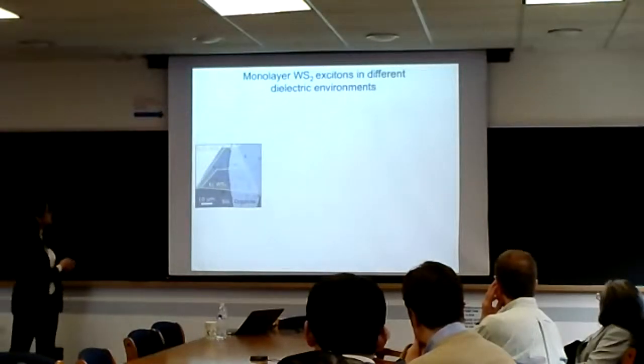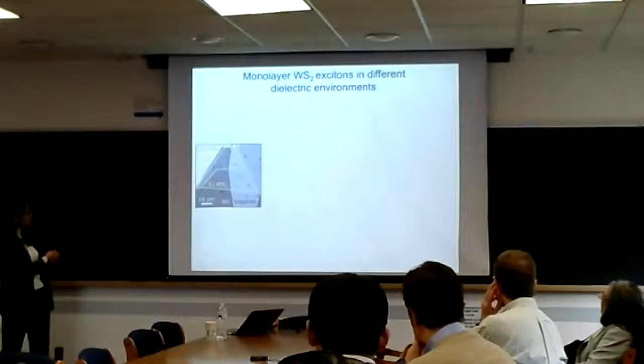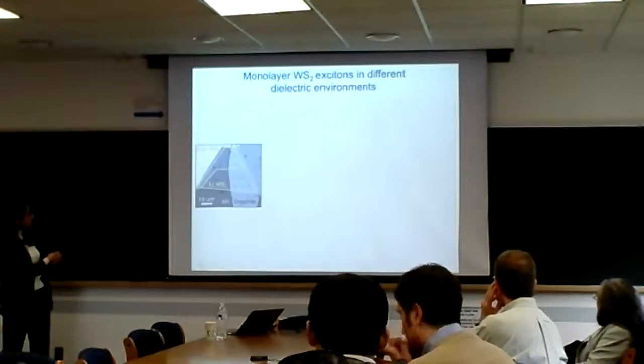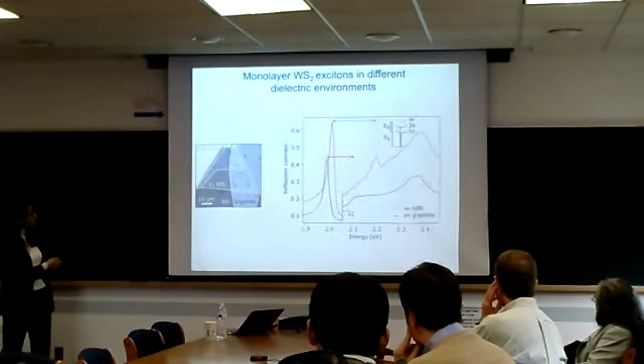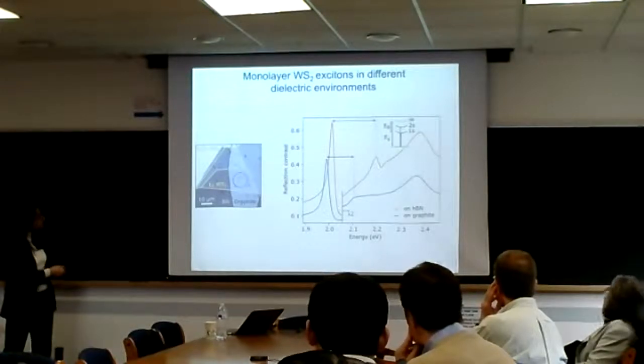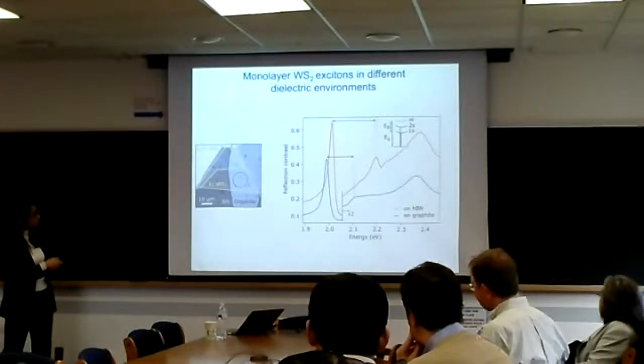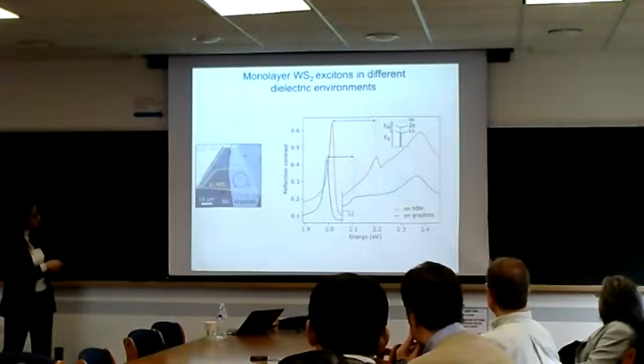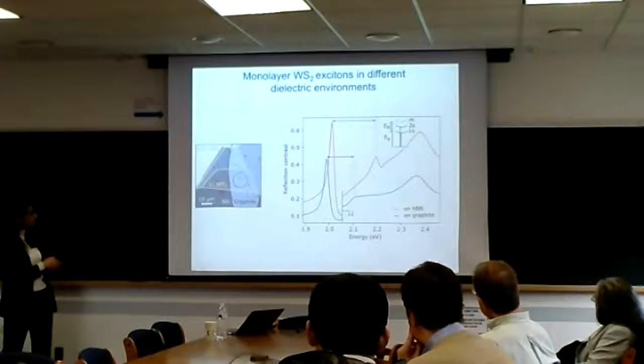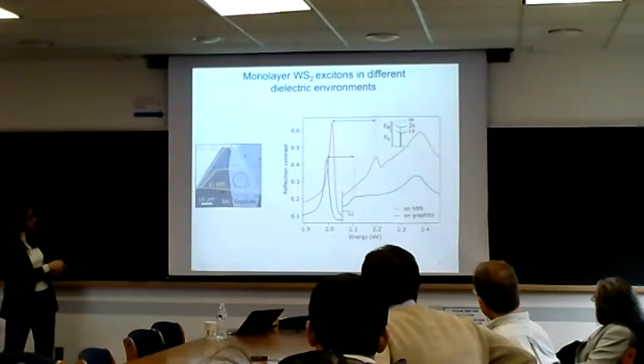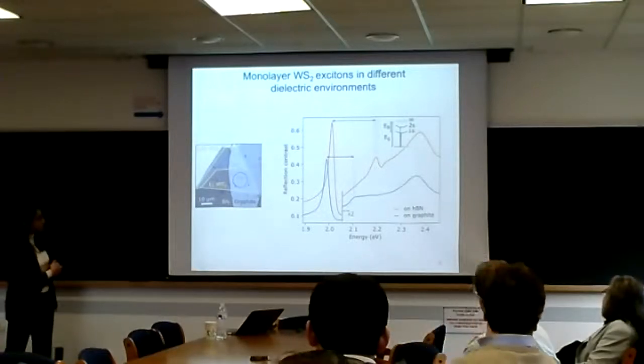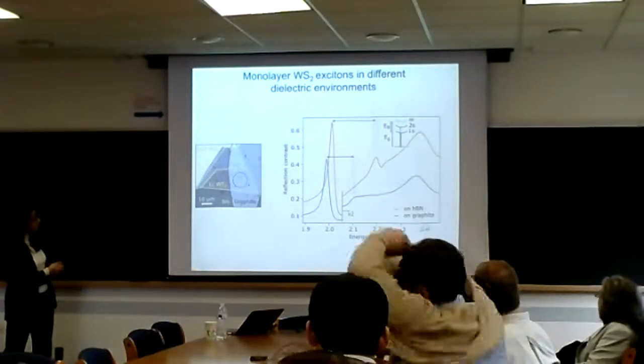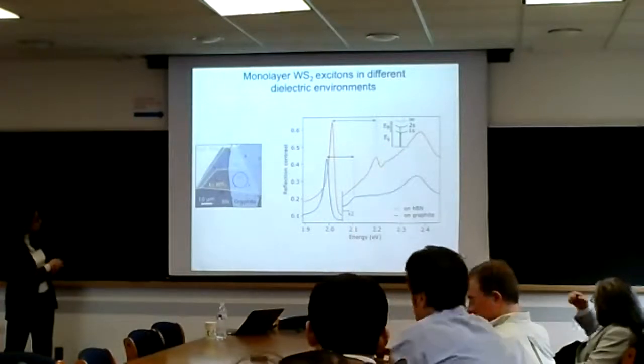So if we look at a system that's here, you have WS2 sitting on hexagonal boron nitride and graphite. Here's some data at room temperature. So you have the A and the B exciton, which is just the spin splitting of the tungsten. But what I want to draw your attention to is this little bump that's in between here. This orange line is the WS2 sitting on BN, and so you have a delta 1,2 that you can see is on the order of 100 meV here,